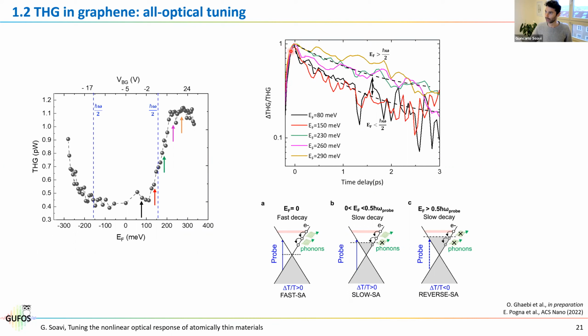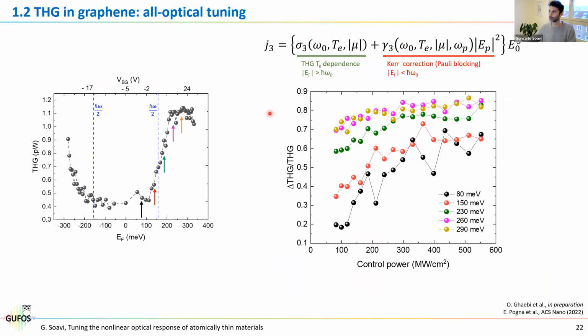In particular, you see that at low values, there is a fast component here and then a slow component. And for large values of the doping, the fast component has disappeared, which means we quench the scattering with optical phonons. Okay, but now let's move forward to the origin of this all-optical modulation. And we can do that by tuning the control power. Now, the interesting part, and I cannot give you too many details on this because we are still working on the theory, but the interesting part is the following.